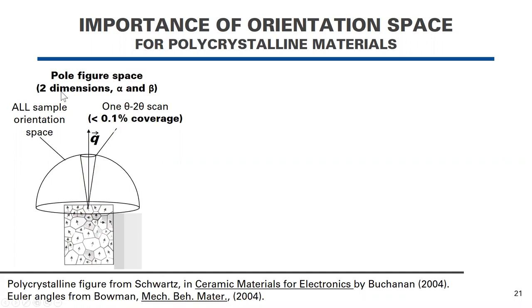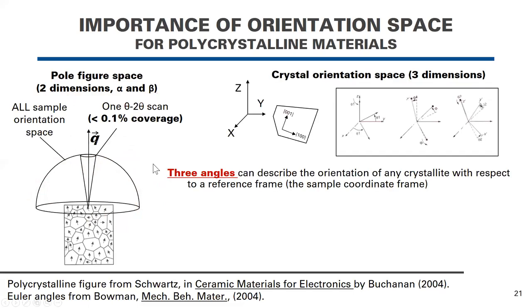And so you could approach this from a pole figure perspective, where you have two dimensions, like shown in that cross-poling paper I referenced before, those two dimensions being alpha and beta. And you could consider, instead of just selecting one orientation, we might be able to measure the entire pole figure. And that would provide more value to the types of things that we want to characterize.